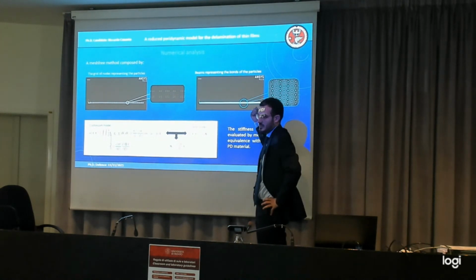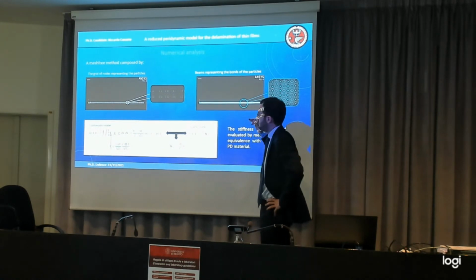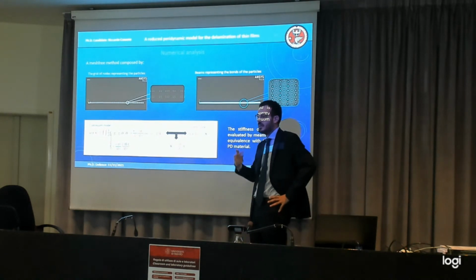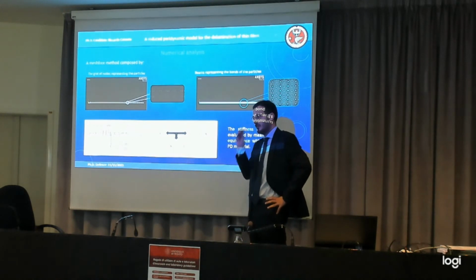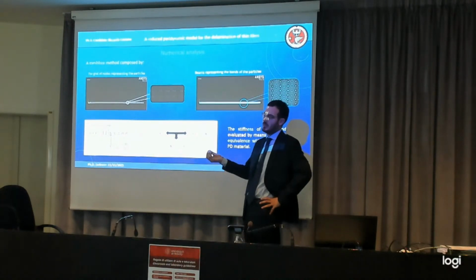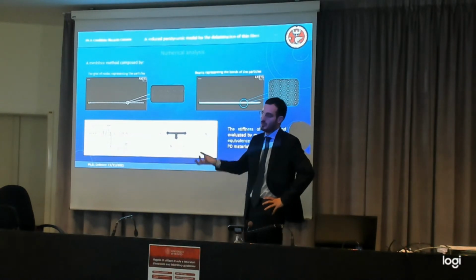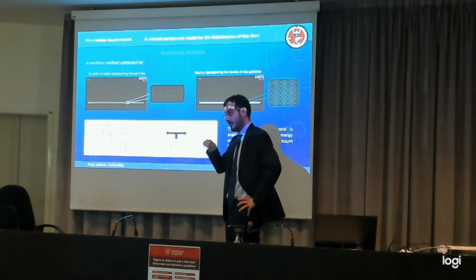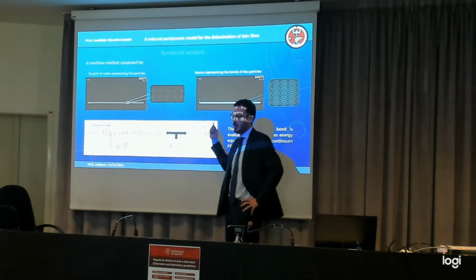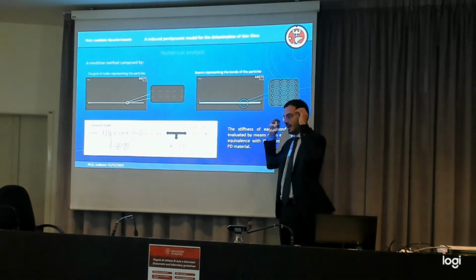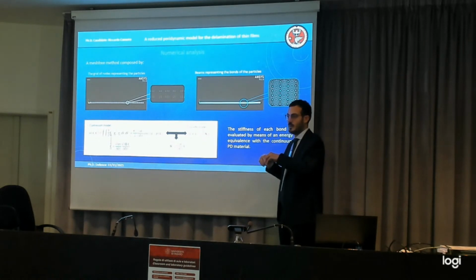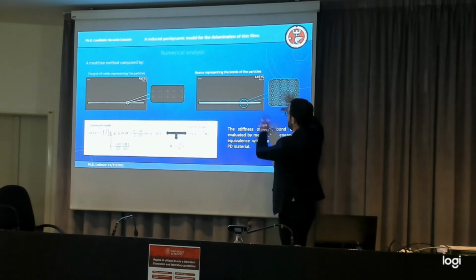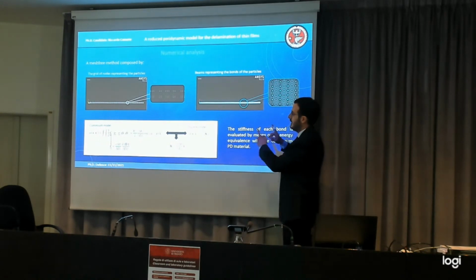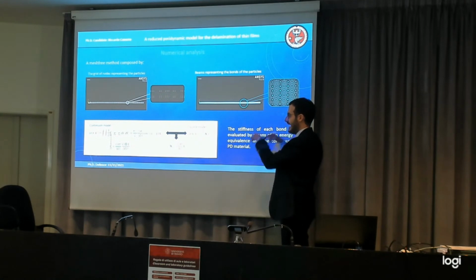order to write out this number, this K, you have to calibrate this parameter, and typically it is done by means of a volume integral of the non-local energy. So you want that the specific volume energy of the peridynamic model resembles that of your local material that you want to reproduce. And by doing that, you actually have to integrate over the volume. So the shape and the connections directly affect that value. So all the microstructure and the extension of this grid depends a lot on the maximum distance at which two particles can interact, which is called the horizon. And the shape of the horizon directly enters the integration.